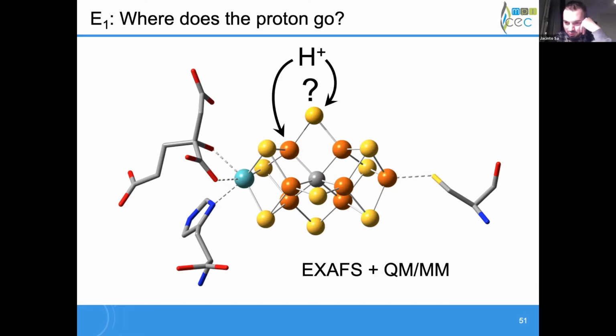Then Jerry has a couple of questions I will read because he cannot speak. The first one is about the resolution. How much energy resolution do you really need to get sharpening of the features in HERFD? There are higher solid angle options at 2 to 4 eV, than at 0.5 to 1 eV resolution. Yeah, so for us, we wanted the HERFD particularly for molybdenum, because looking for those changes in oxidation state at molybdenum from partial fluorescence yield, you're going to see just subtle shifts around. You might get it if you have a real shift in the edge, but HERFD is really critical for that. From the iron perspective, it's nice, but it's not as critical. So this is why we also chose to go with the partial fluorescence yield experiments for solving that problem.